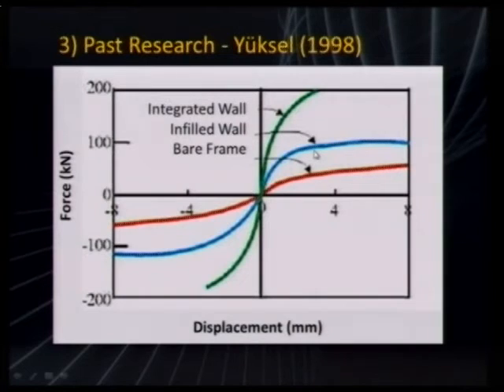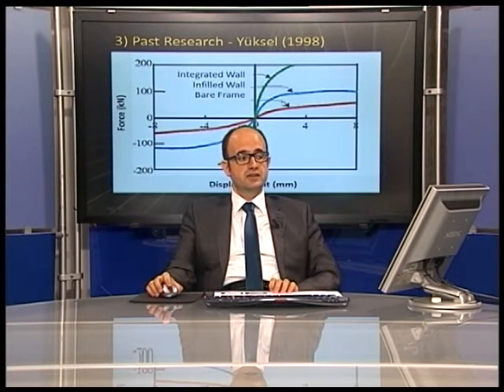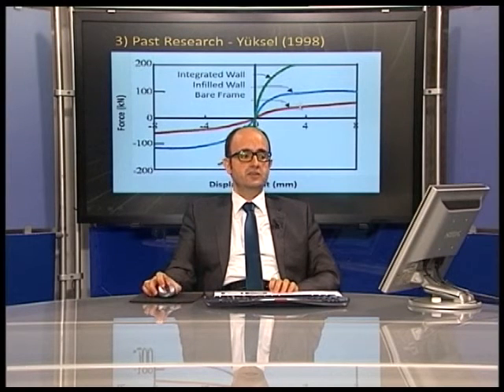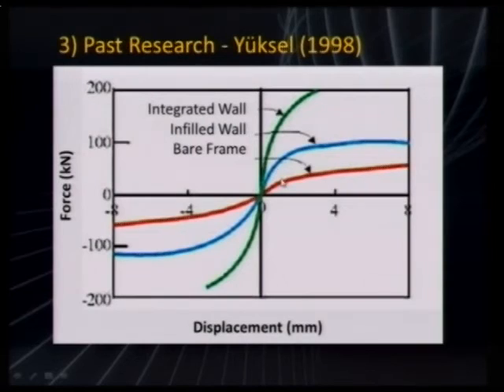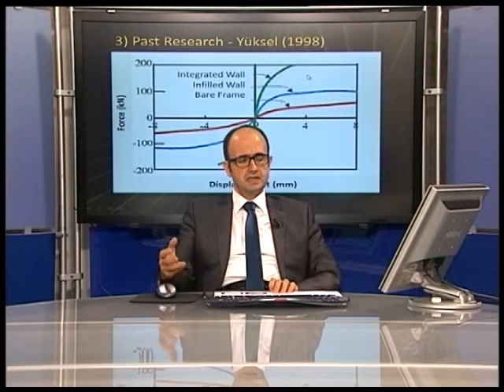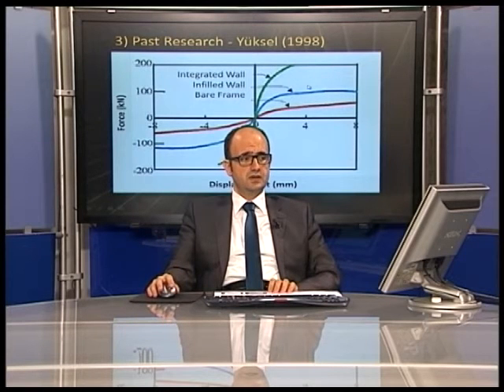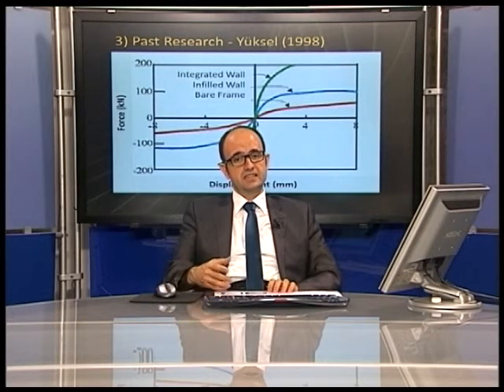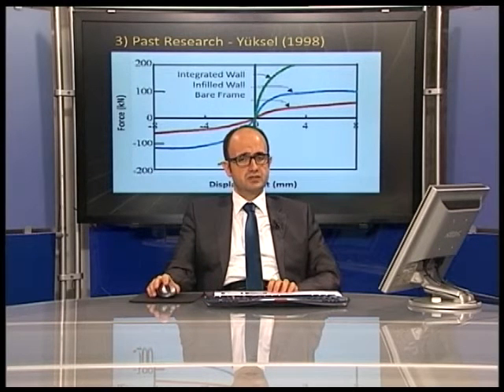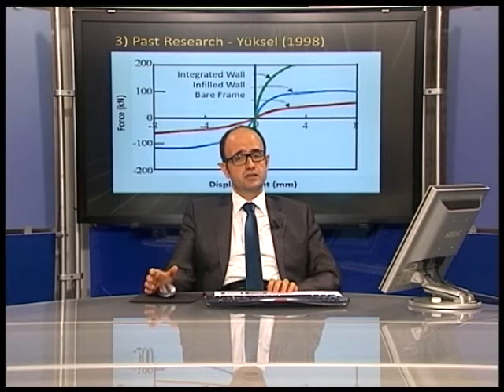But when you change the construction style, like integrating the infill wall, I mean making the casting together so that the concrete goes inside the infill brick elements, the strength increases very highly compared with the bare one. And also the stiffness of the structure increases very highly. We can say that this study is a milestone study of our researchers, showing that when you are successful enough to integrate the infill walls to the RC structure, the earthquake performance of the RC structure may increase tremendously.